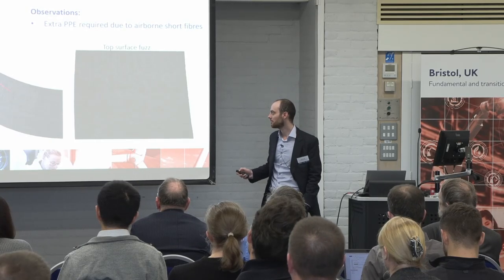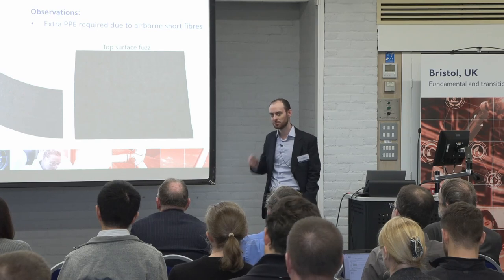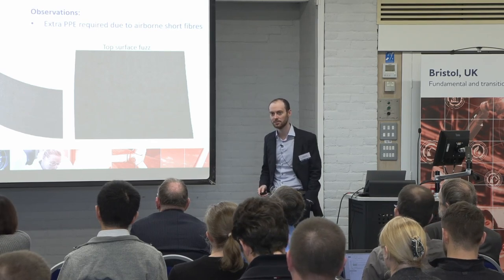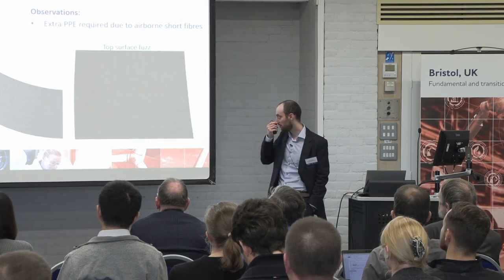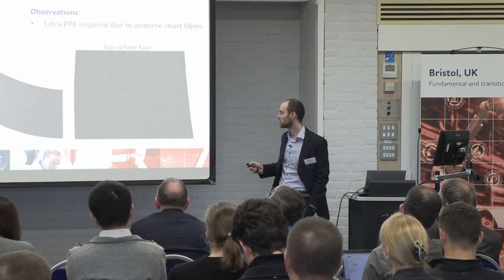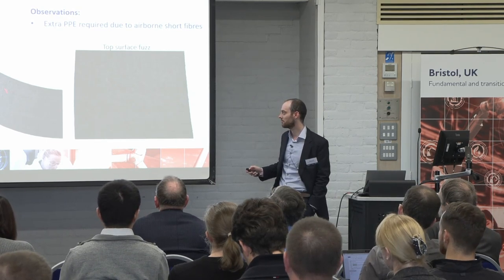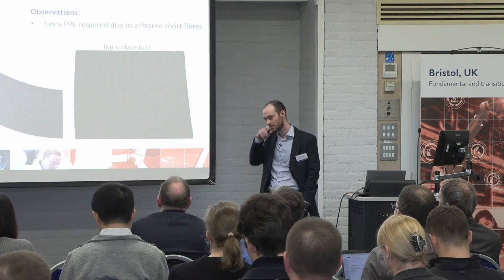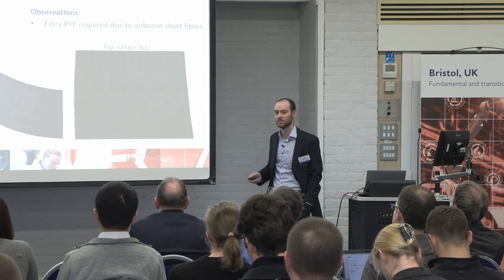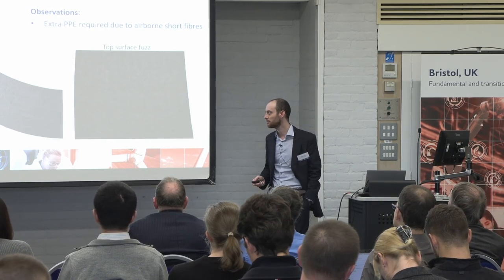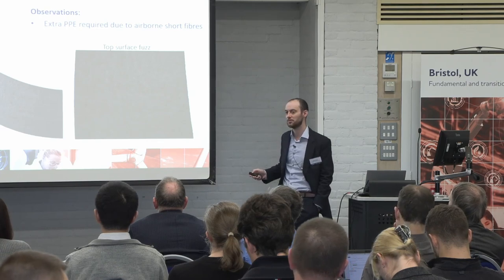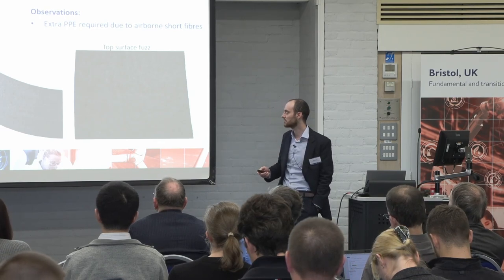We saw some very minor features. They wouldn't really hit on the defect scale that we typically expect for aerospace. But nevertheless, we're working on slight shear wrinkles due to the low tensions needed and a little bit of dry fiber fuzz, which I think Lineat are already well on the way to eliminating. So it was a very, very good result and again, the first of its kind.